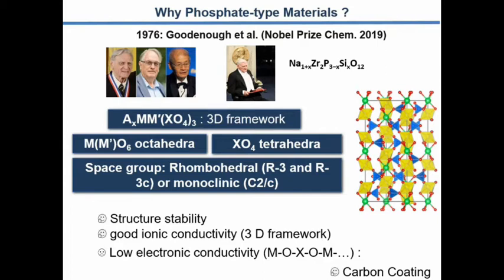We have some octahedra, some tetrahedra, and we have this 3-dimensional network. We have also a wide range of space groups, from R-3, R-3c, or monoclinic C2/c. We have also some 3-dimensional pathways for lithium diffusion.